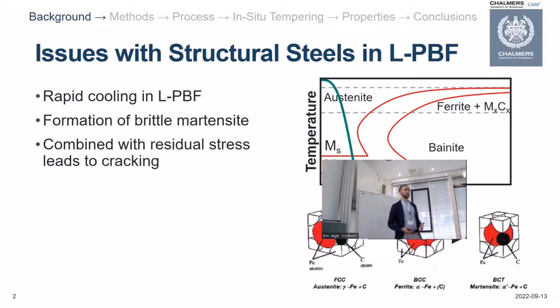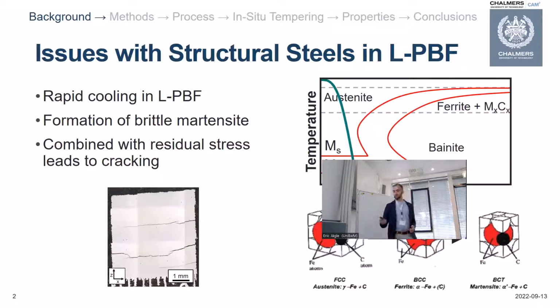So I'll first talk about the process development that we did to try to find high density crack-free specimens. I'll then talk about, and this is why it fits into the session, how the in-situ tempering that the process of LPBF provides allows us to achieve this. And then finally, I'll be talking about the mechanical property performance of these alloys when you're able to make them high density and crack-free. Oh, yeah, and just to quickly show you, these are the nice big cracks you have in these materials. So it's a little bit of a problem.